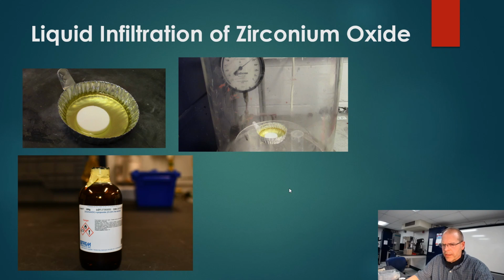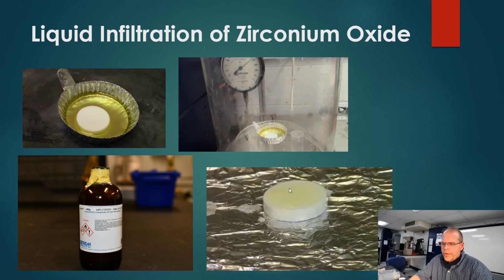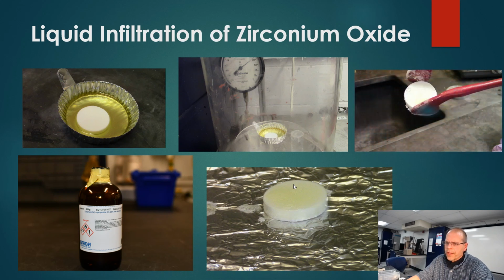Regardless of how we end up doing this to get the right amounts, when we're done, we are actually going to take the disc out of the liquid and flip it over, put it on a hot plate for a little bit, low temperature, and try to evaporate off some of that alcohol in that precursor and let it dry. And then when we're done, we actually will do the reverse. The side that was sticking up will then go down in the liquid and vice versa. So we'll do the other side similarly. And hopefully we'll end up with a disc that's absorbed the zirconium oxide through this liquid infiltration process.